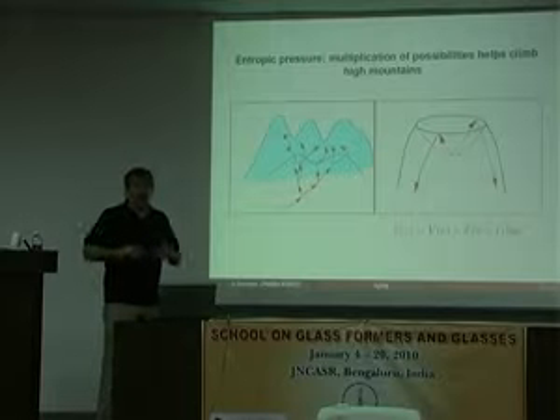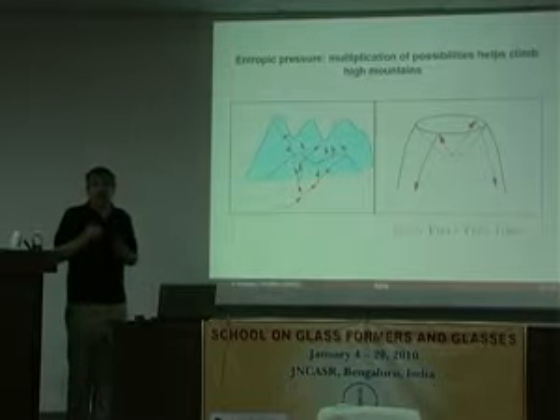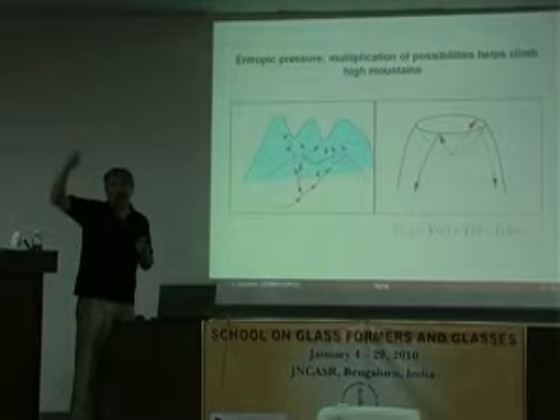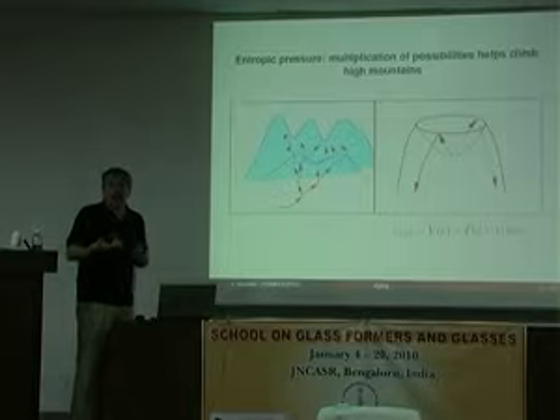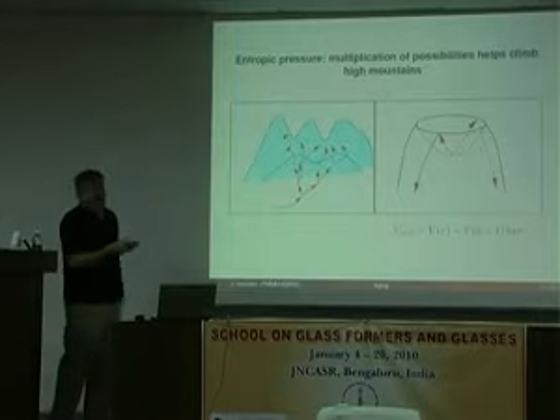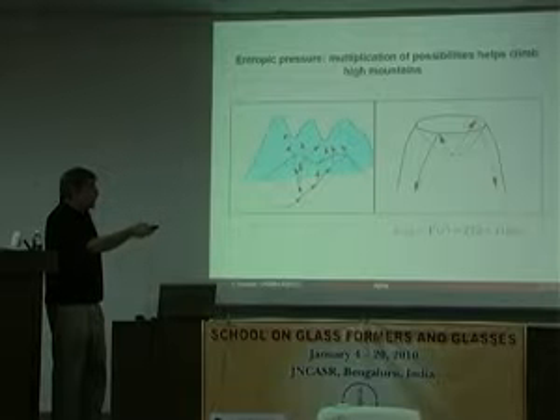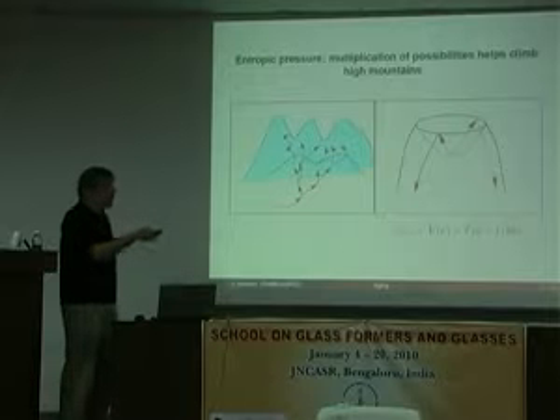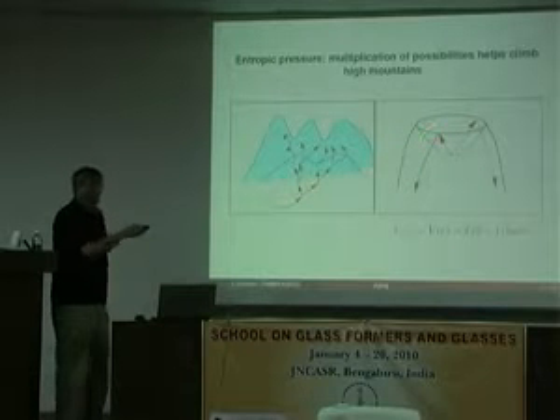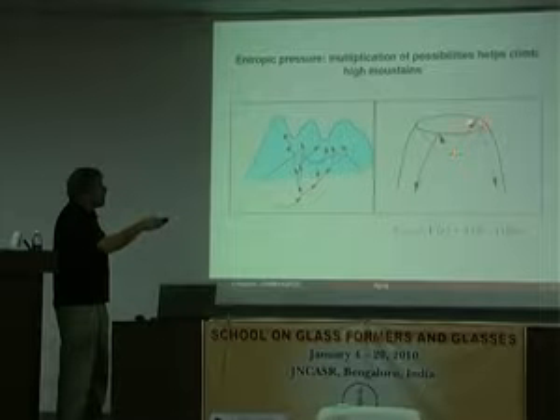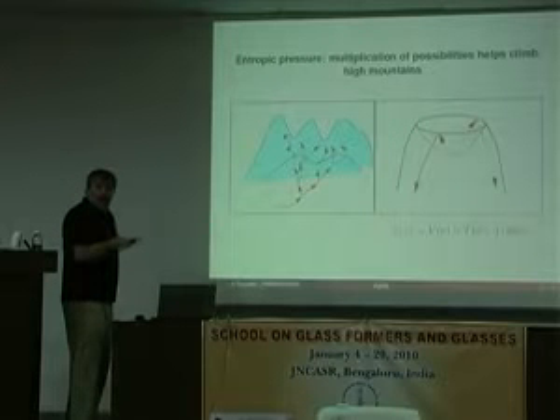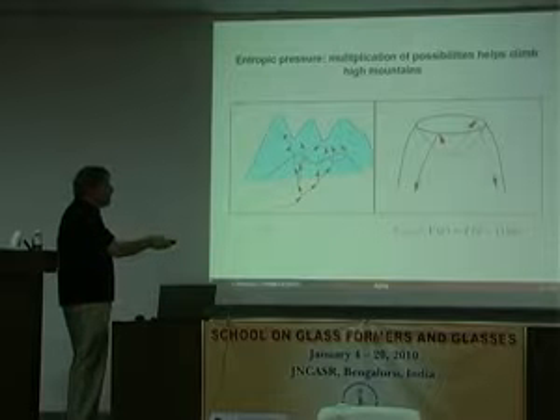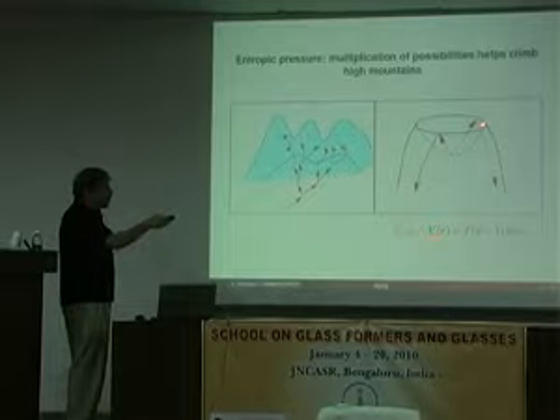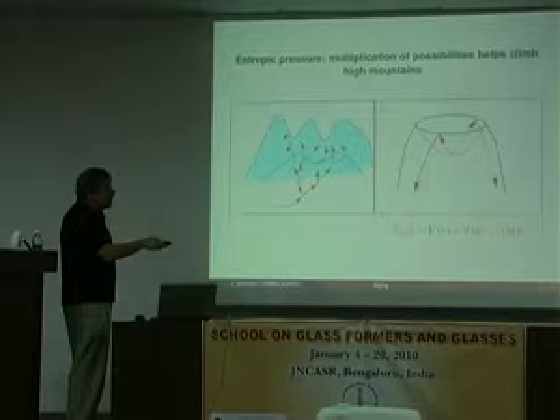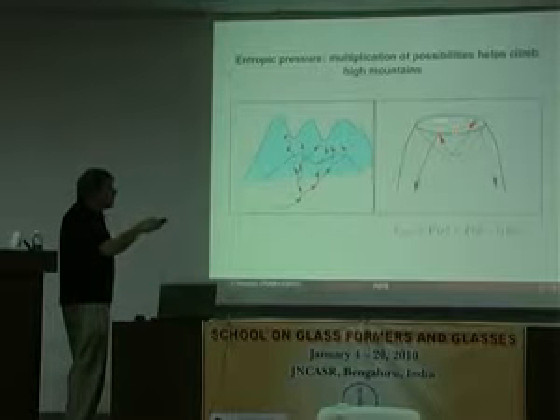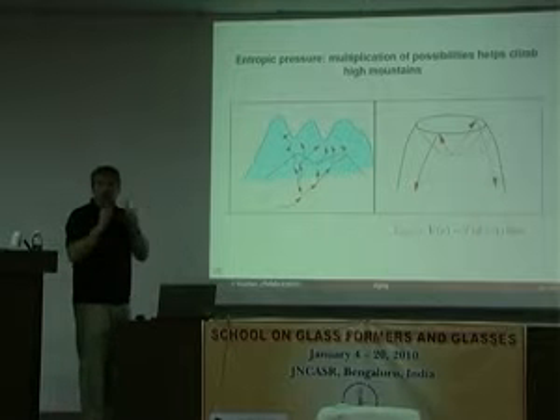But normally this is a bit obvious, but it's also a dynamical argument. And in a way, when you do a replica kind of calculation, this comes in automatically. You get a barrier that takes everything into account automatically. You can make it also dynamically in the sense of this multitude of barriers. Let me tell you this little exercise, which is very nice: you can take a normal Langevin equation, where you're calculating an Arrhenius thing, and do it for this spherically symmetric potential of escaping here. So normally you would get the exponential of this height. But when you do it with a perfectly spherical thing, you can go to spherical coordinates. It's not very hard. What you get is an Arrhenius passage with the potential height of the barrier, but corrected with this term, d minus 1 log of r, which is nothing else than the logarithm of the volume of the rim you're trying to pass.